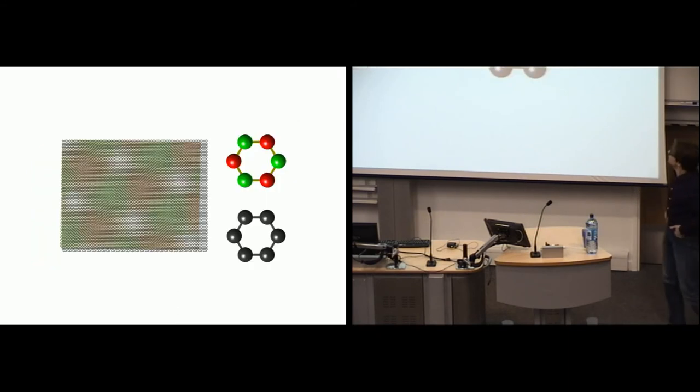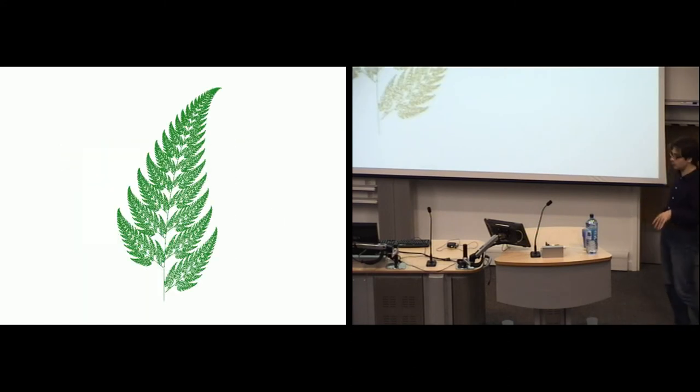And a very simple example of such a sandwich is graphene put on boron nitride, they are both made up of hexagons of different atoms, the hexagons are of slightly different size. And it turns out that when you put that in magnetic field, electronic spectrum is fractal, that means that it's built of self-similar repeating patterns, a little like the pattern here on that leaf.